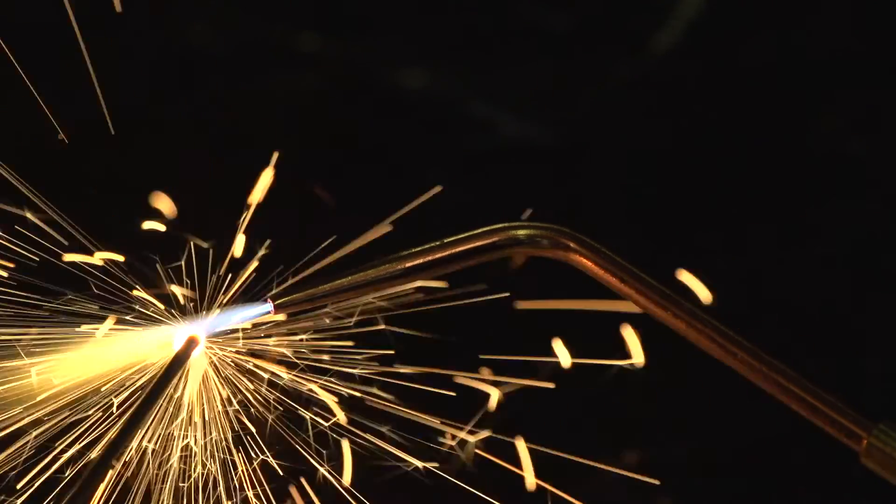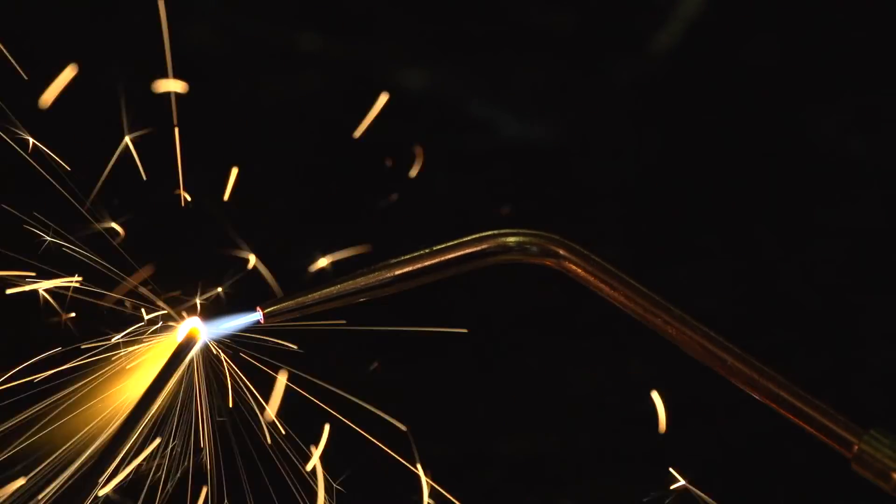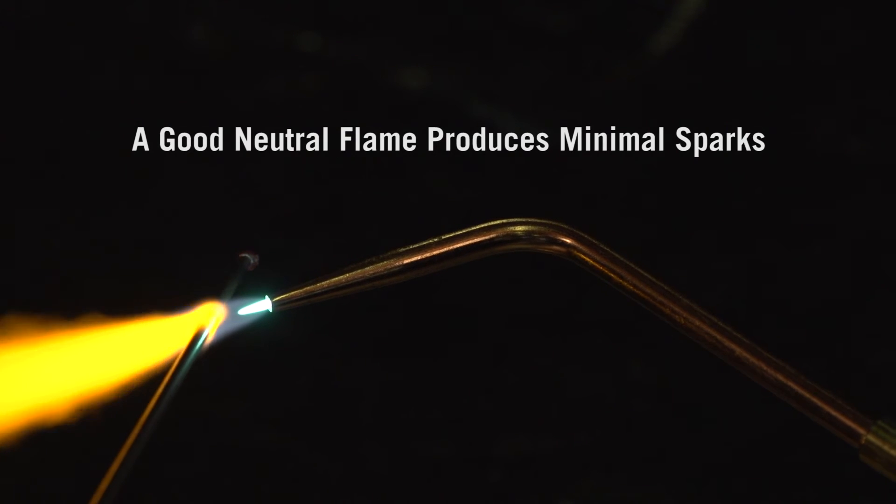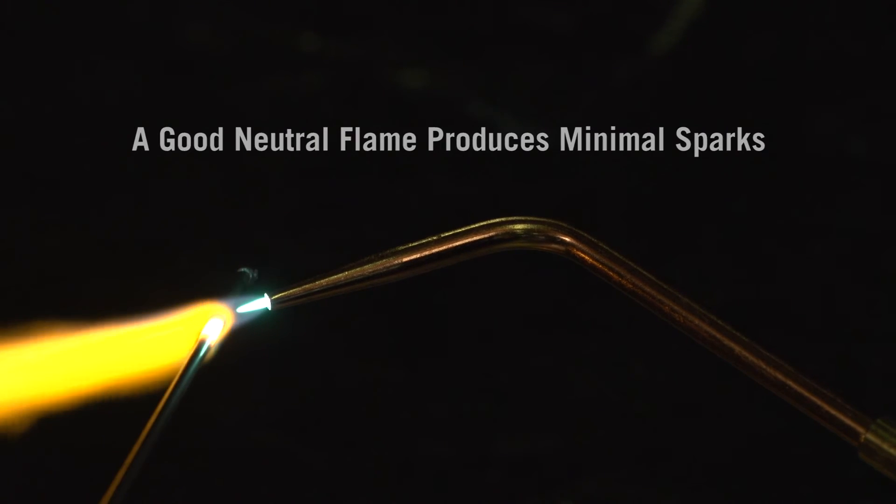An oxidizing flame also creates excessive sparks when you add filler rod. A good neutral flame produces minimal sparks and it's the flame you want for oxy-acetylene welding.